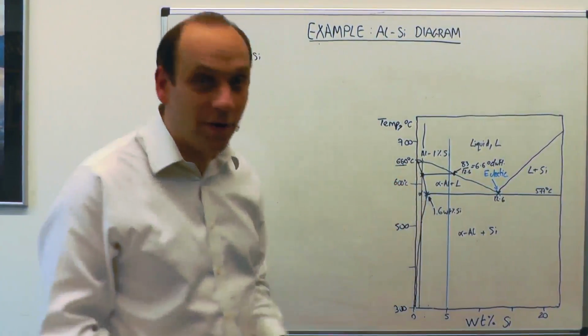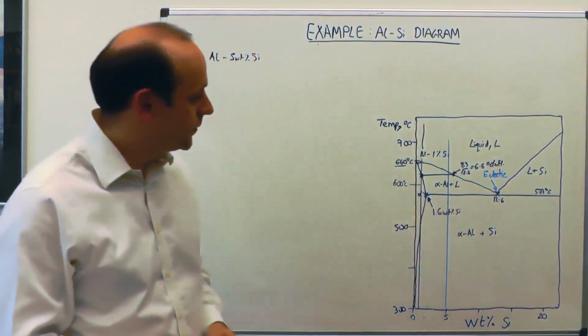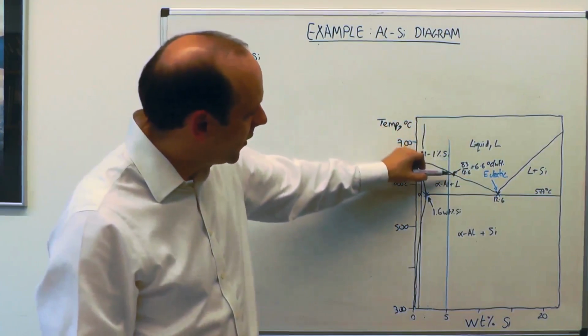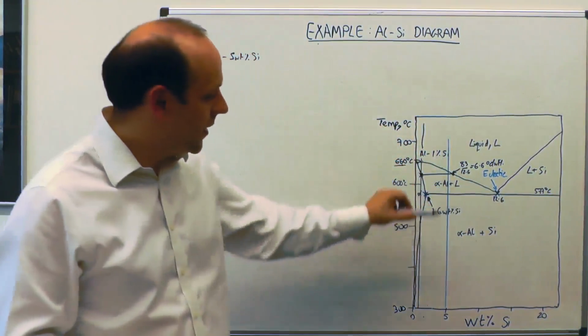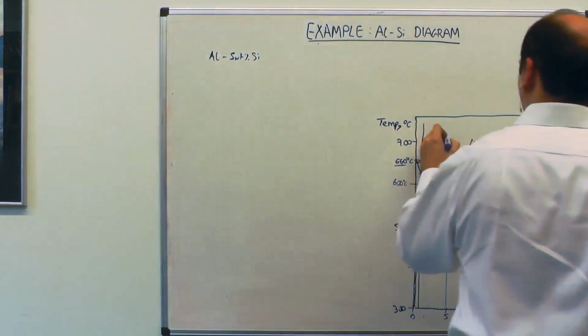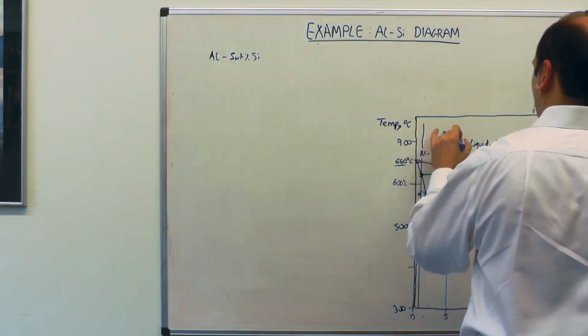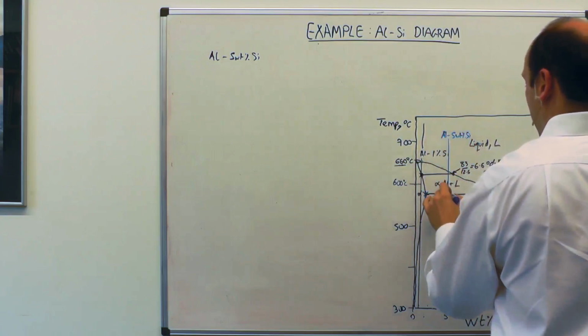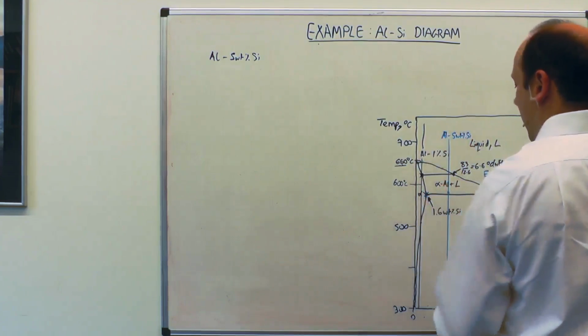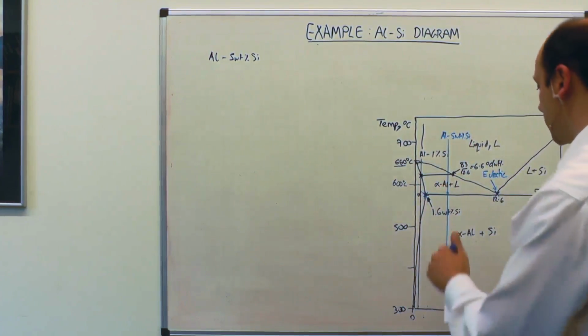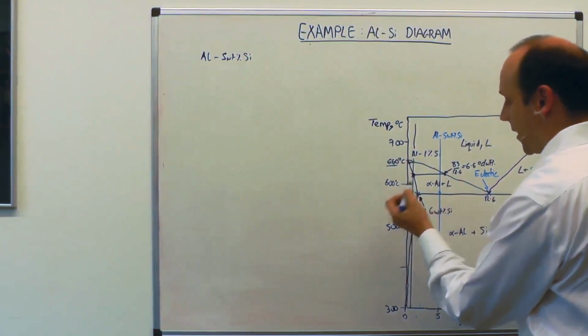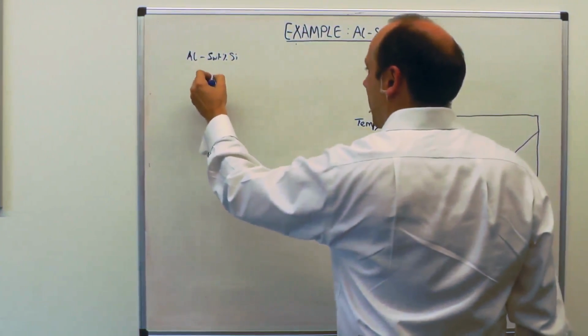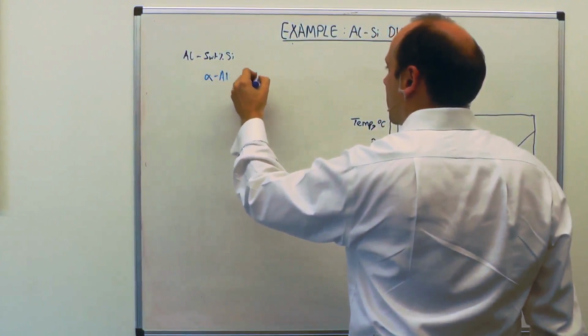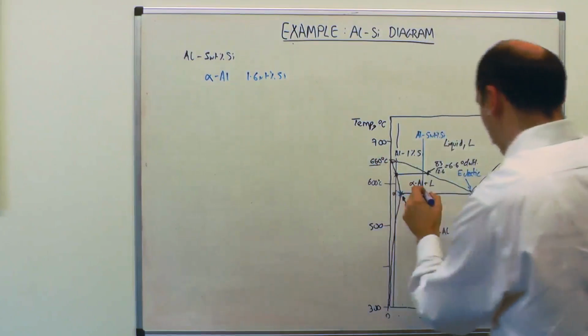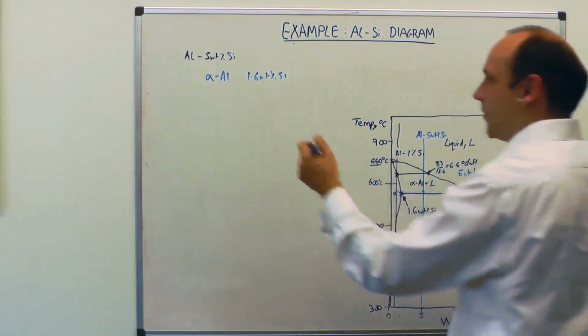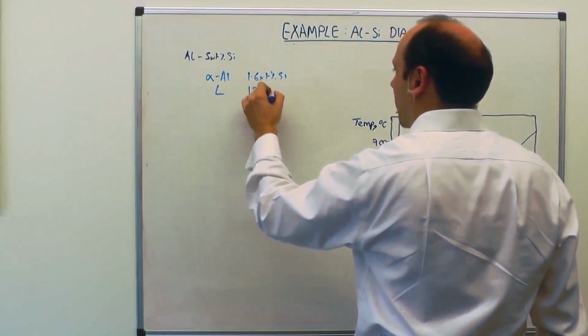So at 578, we're just above this line corresponding to the eutectic. We've come down from the liquid and we've formed alpha aluminium plus liquid, and now we're just above that point. So that's our alloy, 5% silicon. So here at 578, we're just in the alpha plus liquid regime. And the composition of the alpha will be over here, so that'll be 1.6 weight%. So we'll have alpha aluminium at 1.6 weight% silicon. And we'll have liquid, which is over here very nearly at the eutectic point, which will be at 12 weight% silicon.